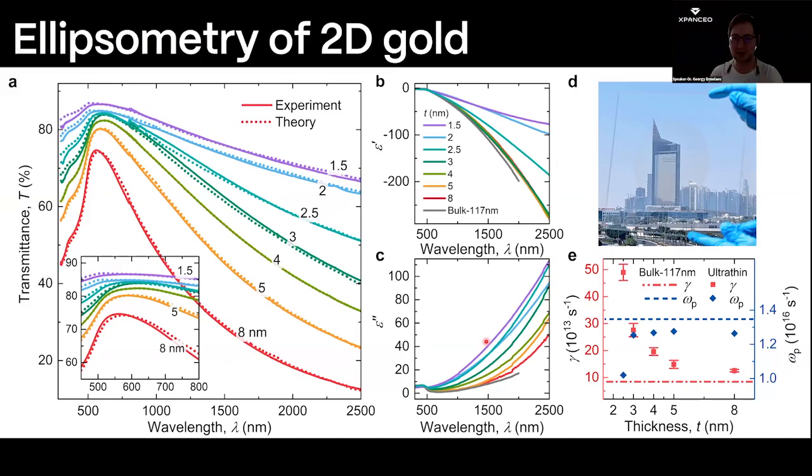We already know the thickness from the deposition system, where we are measuring it using the quartz mass system, and we also verified this thickness with atomic force microscopy. But you're right that if we wanted to try to fit the thickness, it would be overfitted and we would not get reliable results. So that's why we need to know the thickness in advance before modeling. That's correct.